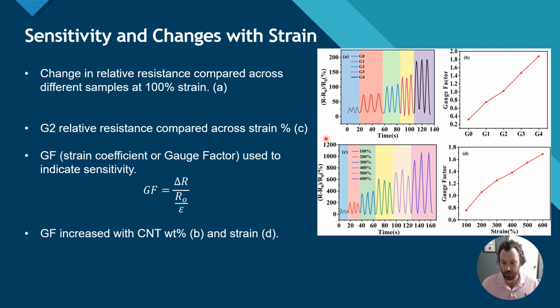You'll see that with increasing carbon nanotube concentration, and therefore increasing conductivity, as mentioned before, the relative resistance increases at 100% strain from G0 to G4, with no critical carbon nanotube percentage showing itself. This was also done with the gauge factor, which is essentially a comparison of the relative resistance divided by the elongation ratio, which is a standard for hydrogel polymers to look at the conductivity with the effective strain. And you'll see a linear relationship here, yet again, with the increasing of the carbon nanotube percentage.